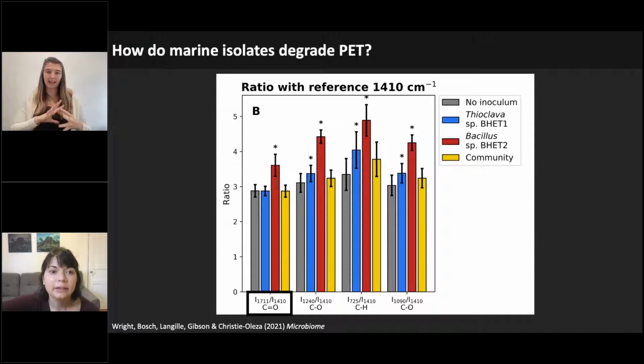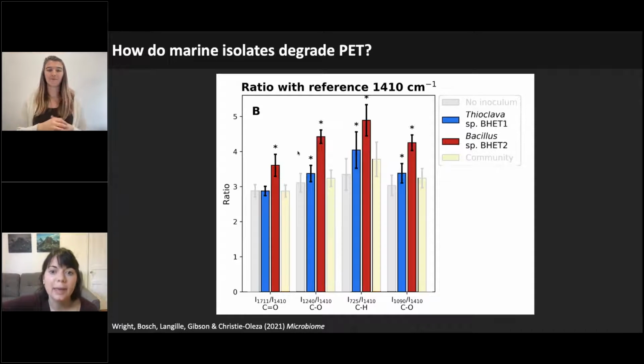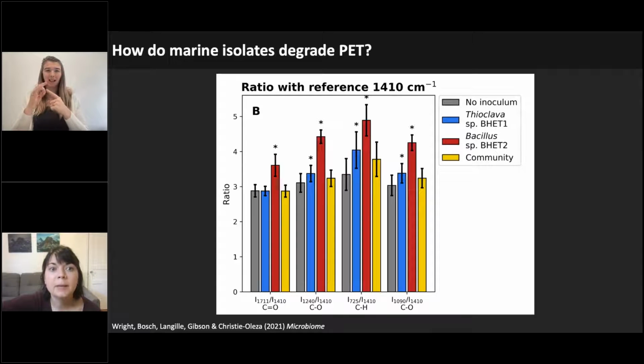So what we see is that we have increases in the surface oxidation for PET that was incubated with both Thioclava and Bacillus, in blue for the Thioclava and red for the Bacillus respectively. But the much larger increase in oxidation that we see for Bacillus is in accordance with the non-specific oxidation that we suggest is probably taking place. And you might notice here that with the community, which I've shown in yellow, some of these ratios are increased relative to the controls with no inoculum, which is this grey here, but none of these increases are statistically significant.